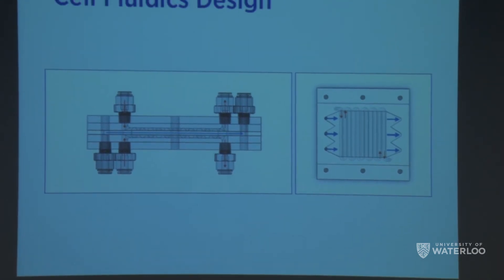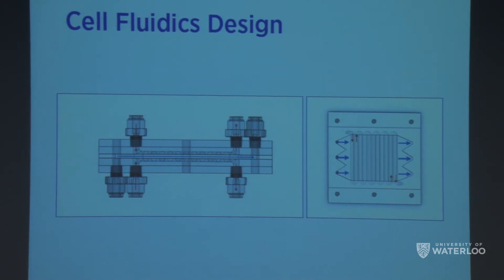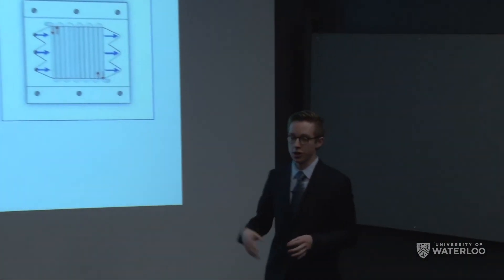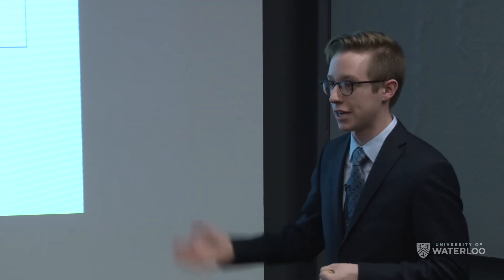So we took a fairly counterintuitive approach and added salt to the slurry. Adding salt to a desalination system doesn't seem to make sense, but when added to the slurry behind the ion exchange membrane there's no chance of it diffusing back into the feed water, and it drastically increases the conductivity of the material. With this understanding of the slurry, another important design feature was a serpentine channel in the current collector. The reason was to ensure effective mass transport through that high-aspect-ratio cross-section electrode, covering the same interfacial area with a smaller channel to effectively move saturated carbon out of the electrode.